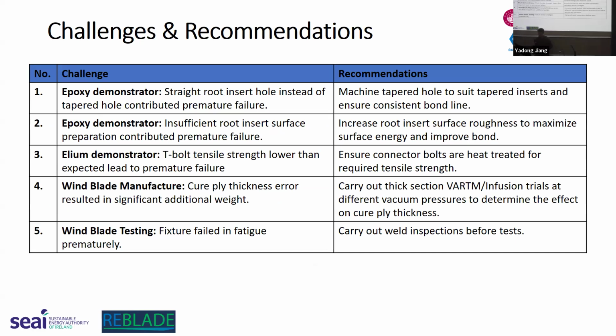So the carrot-shaped root insert on the epoxy demonstrator, we made a machining error where we drilled a straight hole instead of a tapered hole. So that meant that when we applied adhesive to bond the steel root insert in place, there was a lot of adhesive on the inside of the hole and not so much on the outside. So there was a huge variation in the bond line thickness, which ultimately leads to a weaker bond line. So it's really important that if you're using a tapered insert, you machine a tapered hole to ensure that you get a consistent bond line, that basically means an even thickness all around the components you're trying to glue together.